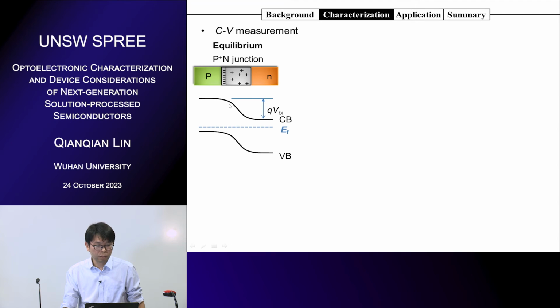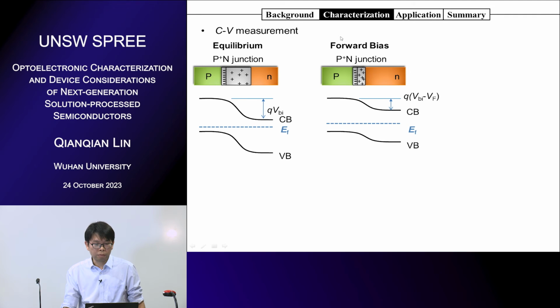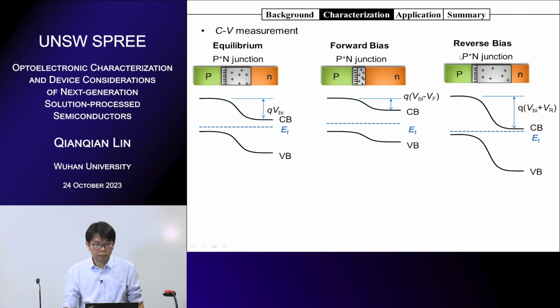Without bias, it has band bending. If you apply forward bias, you will inject carriers, right? Under forward bias you get a higher carrier concentration, then you will reduce the width a lot, and the band bending is not so much as this one. Then if you have reverse bias, the width of the region will be extended, and you have sharper band bending.